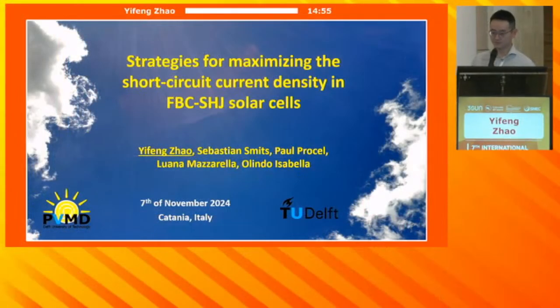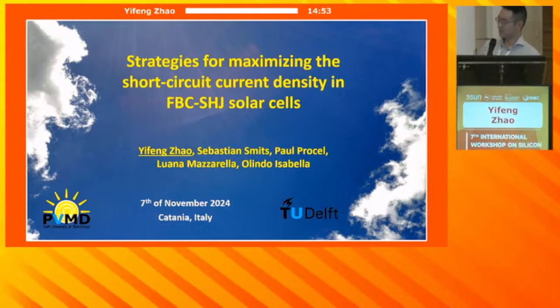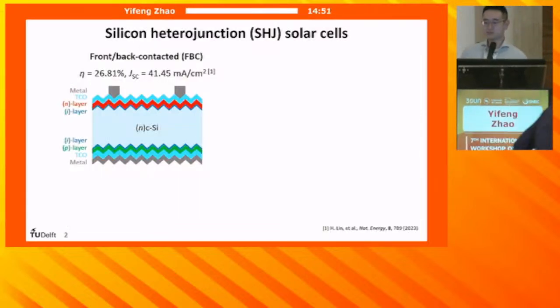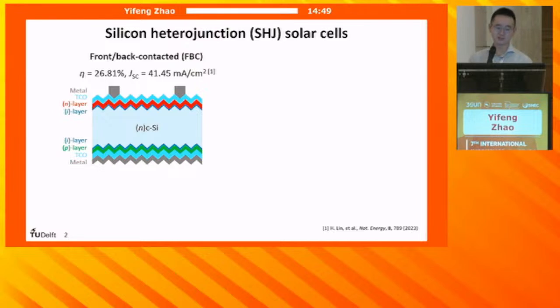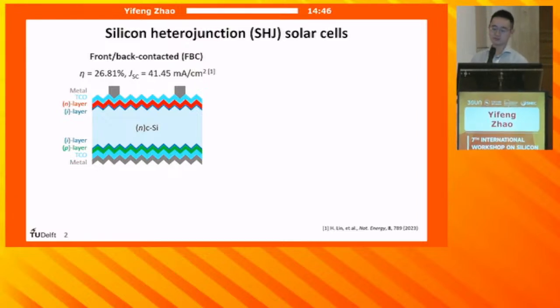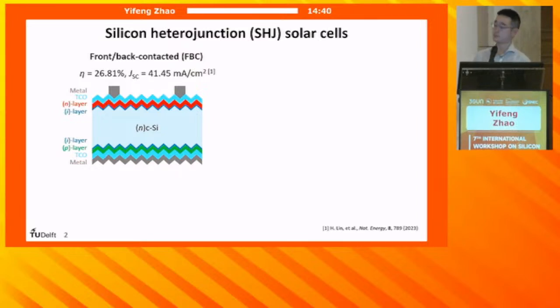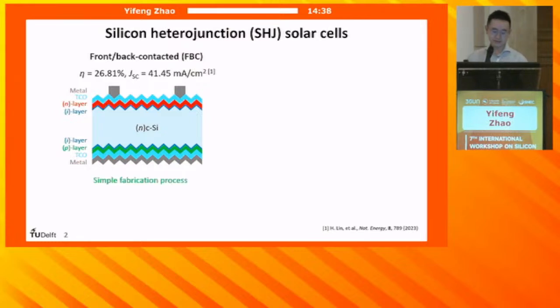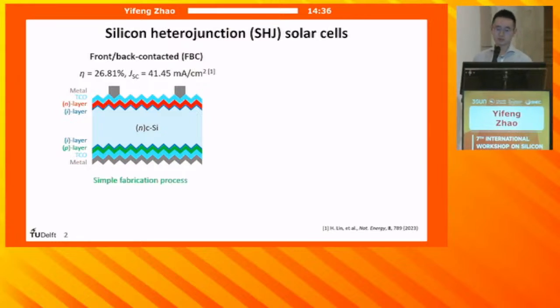Good afternoon, everyone. So let's start. As most of you already know, front-back contacted silicon heterojunction solar cells have achieved a remarkable efficiency of 26.81% and a JSC of 41.45 milliampere per square centimeter. This design features a simple fabrication process, but the JSC is limited by optical losses such as front grid metal shading and also parasitic absorption losses due to the full area TCO and thin film silicon layers.